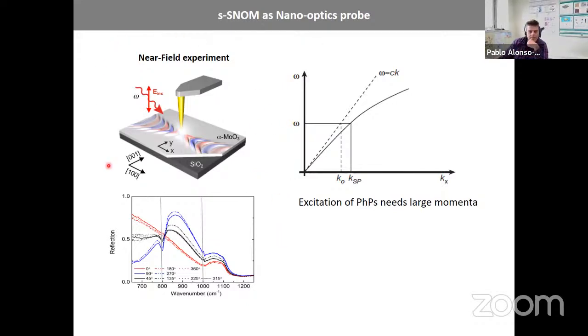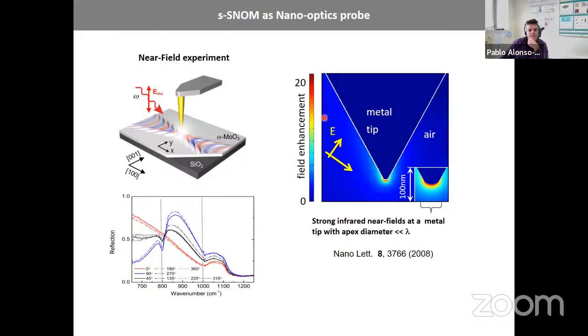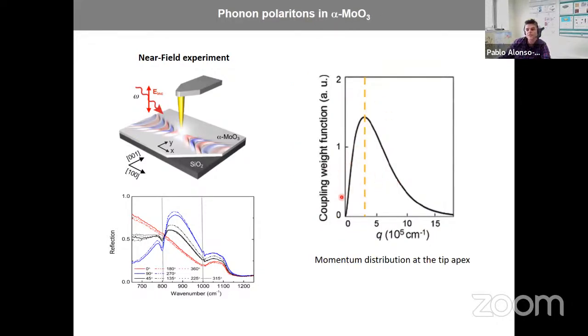So this system, this AFM tip that is illuminated, allows us to provide this high momentum. And how is this? This is a simulation of the electric field in the metal tip when it is illuminated by an electric field like this, and you can see that, by the shape of the metal tip, the electric field is localized here at the tip. When something is very localized, you can see it in a mathematical way: you can do the Fourier transform of something that is very localized in space to momentum, and then you can see that we have a broad range of momenta that can be reached by localizing the field at the tip. So now we have many momenta available that can beat this momentum mismatch and excite the wave. This is the key of SNOM to visualize nano-optics and to excite these surface waves.